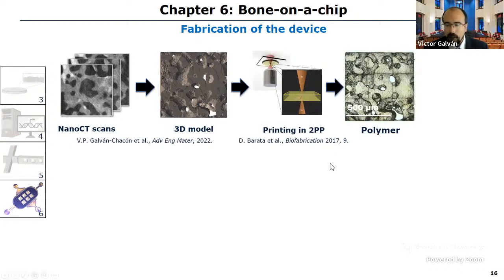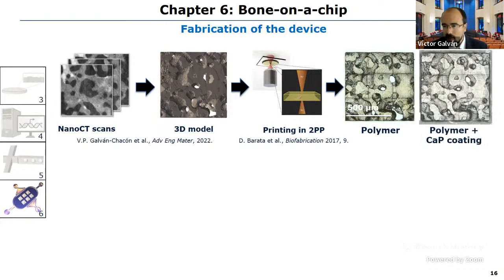In this technique, the materials are usually produced in an acrylic photopolymer, which has a chemistry that is quite far from the chemistry of bone. And to introduce some of the chemical features of bone, we did an enzymatic coating on the materials, and we deposit a very thin layer of calcium phosphate on top of this material without affecting significantly the structural properties.